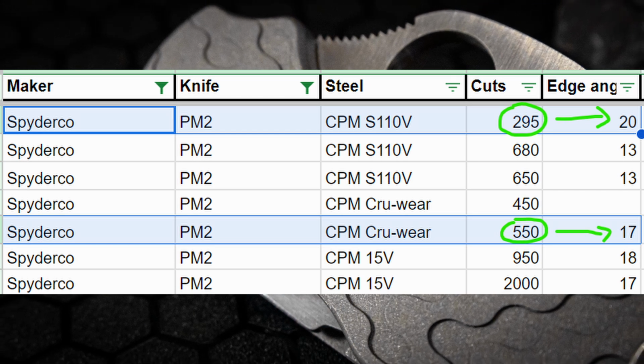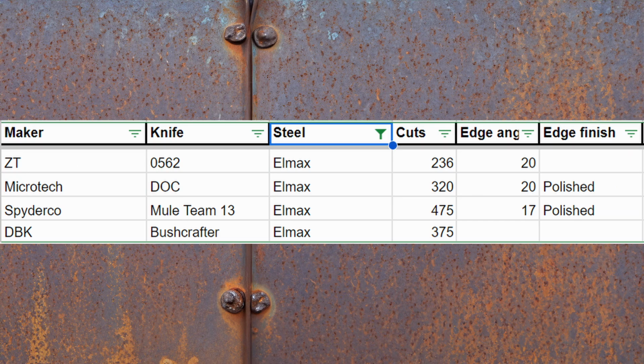In regards to Elmax directly, Cedric and Ada actually tested 4 different knives in this steel, including the Microtech DOC, the ZT0562, and the Spyderco Mule Team 13. Of course, they also did test the DBK Bushcrafter. Out of all of these, the Mule Team 13 performed the best with 475 cuts on a polished 17-degree edge, while the worst performing Elmax tested was the ZT0562, which by contrast only performed 236 cuts on a 20-degree edge.